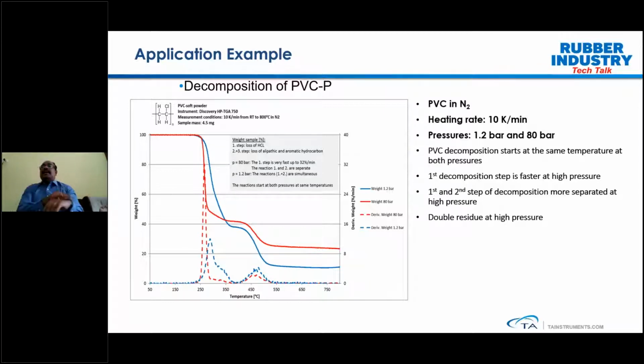So by using these techniques like high pressure TGA, you have an ability to study the material behavior not only with respect to temperature or time, but also as a function of pressure, which gives us a much deeper understanding of the material, and that will help you, in fact, to design your processing when it comes to dealing with a particular polymer, and that will help you to avoid a lot of situations during processing of your particular polymeric material.